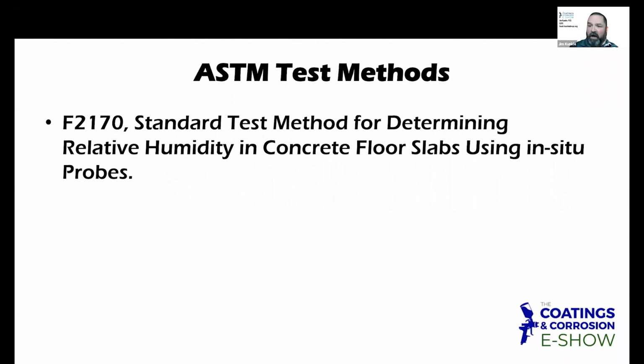Again, these test methods are really just a snapshot in time. Another method that's used a lot in inspection is the F2170, where you're using probes where you drill down into the slab or into the wall and test the moisture using electronic digital methods. These are heavily used today. They are very good at getting a very good definition of moisture. It can be faster because you're able to move and get multiple readings in a shorter period of time, versus test methods where you have to come back a day or after a predetermined amount of hours for the test.